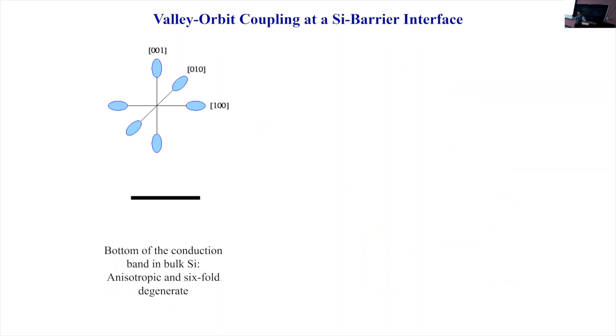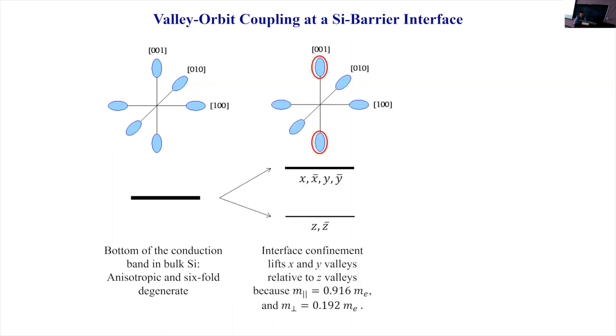Now, our qubits are always residing in a heterostructure, right? So in the typical two-dimensional heterostructure, you have silicon, and then you have a barrier material, whether it's silicon oxide or silicon germanium. So you have this barrier in there with a potential, and that generally lifts four of the conduction band minima up relative to the other two.